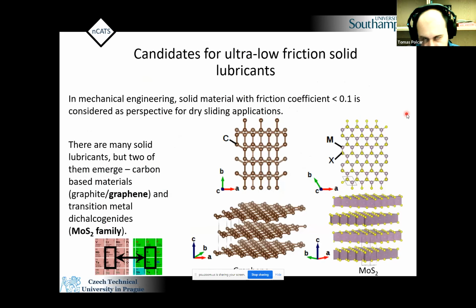So to start with solid lubricants, there are really many candidates for solid lubrication. There are polymer materials, Teflon. You can find a lot of others, but for, let's say, heavy duty applications with relatively high stresses and contact loads, you cannot use those polymeric materials easily, and you have to look for other solid lubricants. Graphite, of course, has been used for many years, and the same applies for molybdenum disulfide. Both of them, as you know well, have a very peculiar structure with very weak bonding between the sheets, so they really allow very easy sliding.